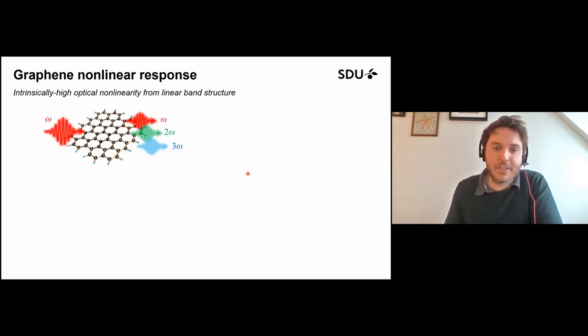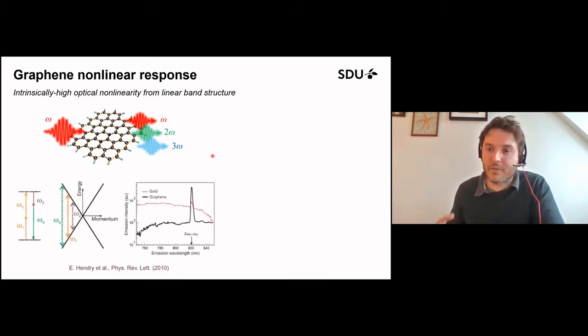And now I should also mention that besides being a really appealing candidate material for plasmonics, graphene is also intrinsically nonlinear. Its response to light is intrinsically nonlinear. So it is actually already quite good for nonlinear optical applications. And a lot of this is already coming from its electronic band structure, which has this linear property. So for example, if you have a nonlinear process where different frequencies of light are involved, either that they're excited with different frequencies of light, or you're generating a new frequency of light, because of this linear structure, you always find a transition going across these two bands that you can couple the light to. And that can already give you some kind of enhancement in the optical nonlinearity.